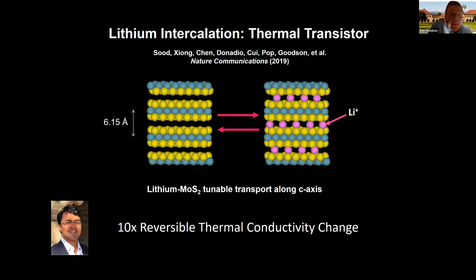Another thermal switch that I'd like to mention briefly is purely solid state. And this is again Aditya Sood and his work together with Eric Pop, Yi Cui, and a number of other collaborators. The idea here is to take a layered structure, in this case molybdenum disulfide, that has van der Waals attachment between the monolayers. And we know that van der Waals forces are not very good at conducting heat.